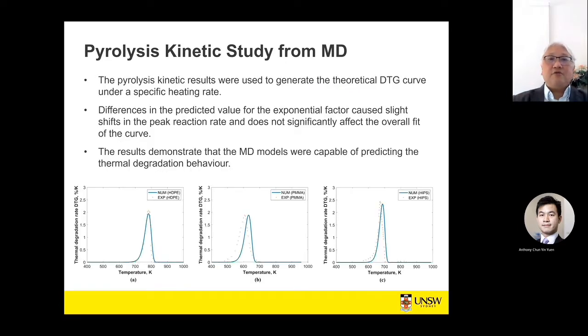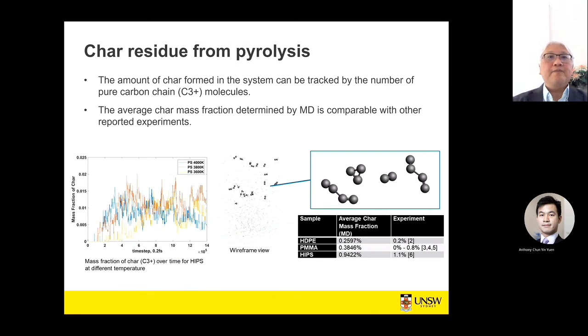So if you look at a comparison in terms of its time degradation behavior, based on the theoretical differential thermogravimetric behavior itself, you can see our prediction using MD comes very close with experiments as well. Now, these figures are significant because they give us confidence that we can use this kinetic rate to be fed into computational models, for example, CFD models and so forth. So what we have done here is that we have gone through a very fundamental route and we could derive useful data as input to the CFD model.